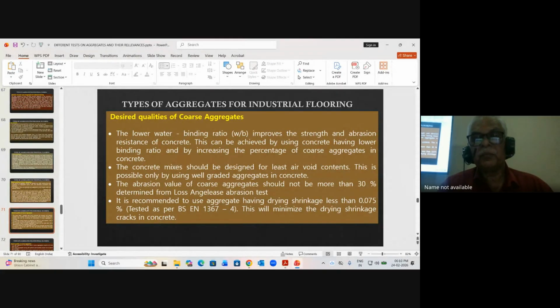Lower water cement ratio improves strength and abrasion resistance, and should be designed for least void content. Coarse aggregate should not be more than 30%. And another thing is shrinkage - it should be less than 0.075% as per this.